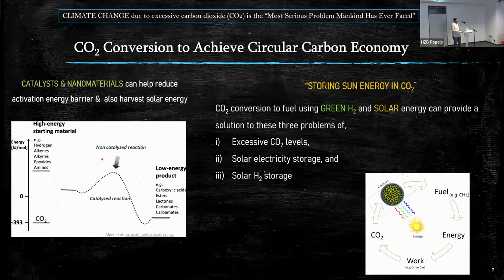And that makes the process unsustainable. So the idea that we are trying to do is, can we develop a catalytic material which will reduce this activation energy barrier? So the idea is you have a high surface area nanomaterial and the CO2 gets activated, right? The bonds, the two oxygens will interact with this active surface. The bonds will get stretched, bent, and that will reduce the activation energy barrier. And then the additional energy that is required should come from the sunlight. So that makes the entire process sustainable. And that's what we're trying to achieve.